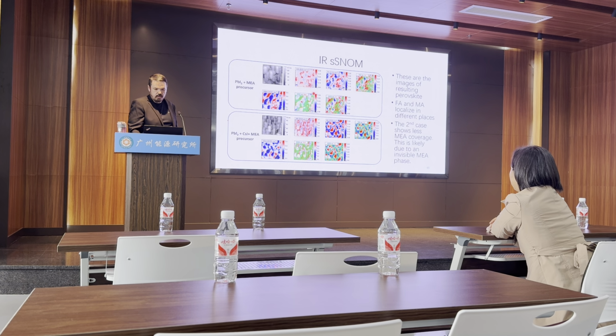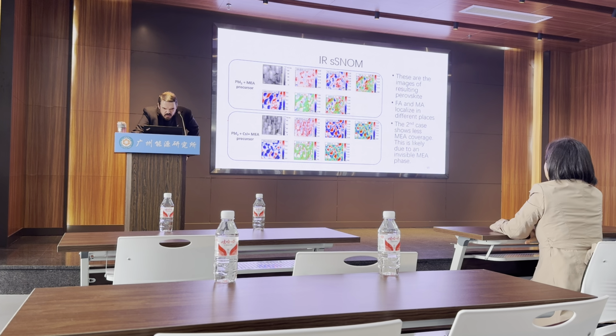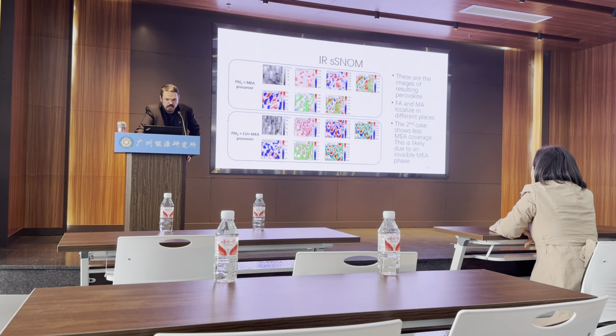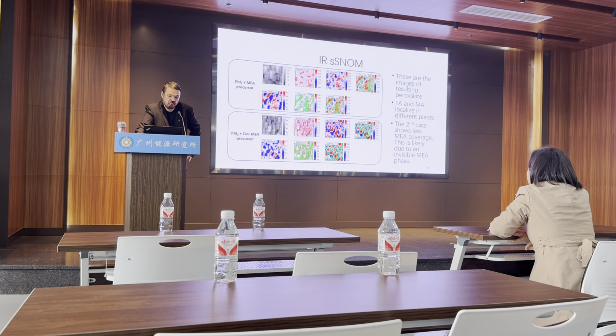Let's just shortly look at the IR SNOM because they are super cool. When we look at the MA and FA distribution, you can see that the MA and FA segregate. That's kind of unusual. We generally don't think that they segregate, but they do. So the black phase is also segregated. The problem is very complicated. They localize in different places. And then we have MEA right here, and this is the perovskite surface, by the way. They add PBI2 plus MEA, and we can see the MEA also kind of localizes in clumps.